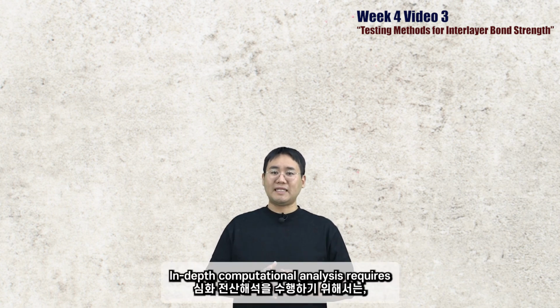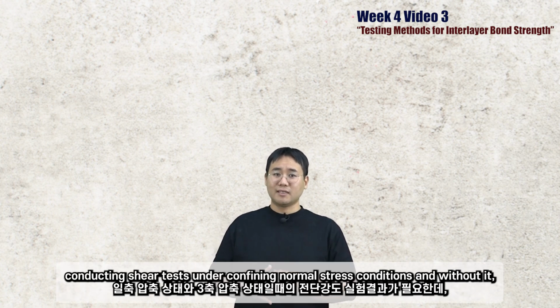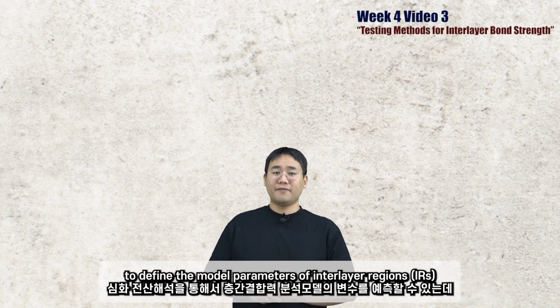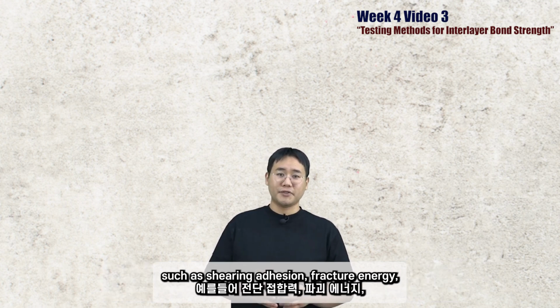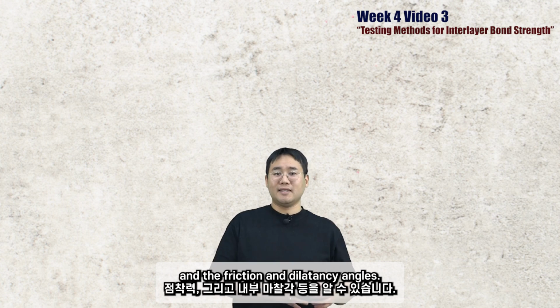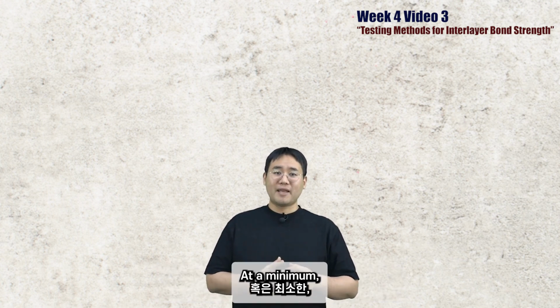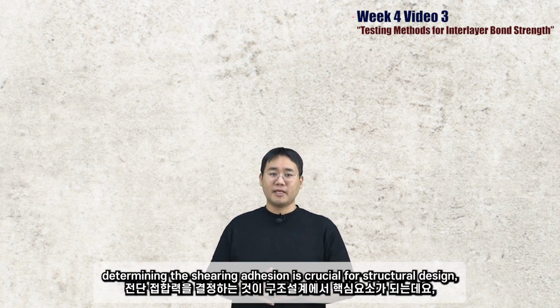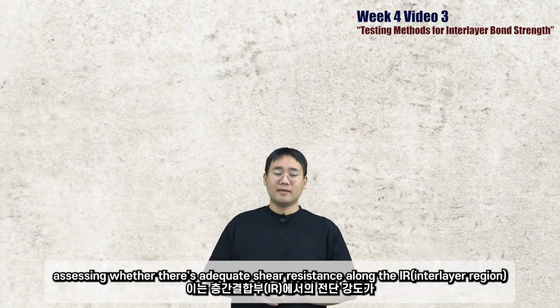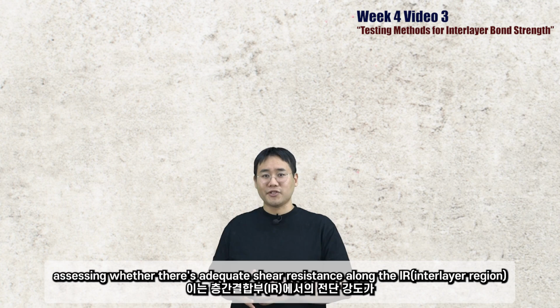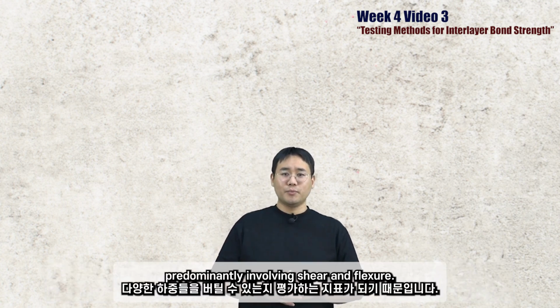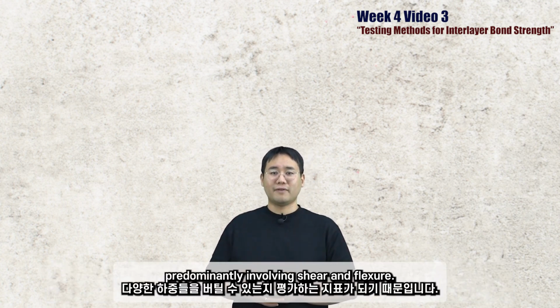In-depth computational analysis requires conducting shear tests with and without confining normal stress, to define the model parameters of interlayer regions, such as shearing adhesion, fracture energy, and the friction and dilatancy angles. At a minimum, determining the shearing adhesion is crucial for structure design, assessing whether there is adequate shear resistance along the interlayer regions to withstand diverse loads, predominantly involving shear and flexure.